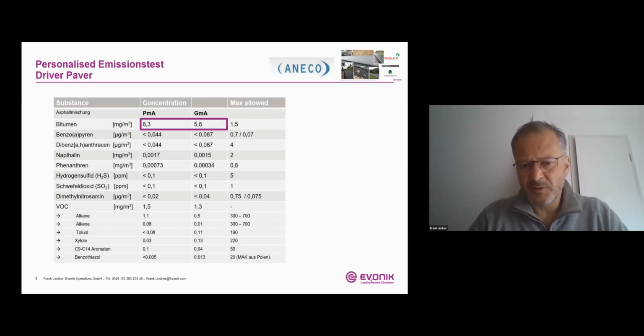We do not see any critical substances, and all the max values which are allowed are no problem for the emissions for both sides, but also not for the rubber. There's one interesting thing, the emission coming from bitumen itself. We have seen a lower emission on the rubber side, something which is not good enough to achieve the 1.5 milligrams per cubic meter, which is the allowed max value starting 2025 in Germany. But again, we have an advantage on our side, and we are studying now to lower the production temperature to further improve the emissions in asphalt.